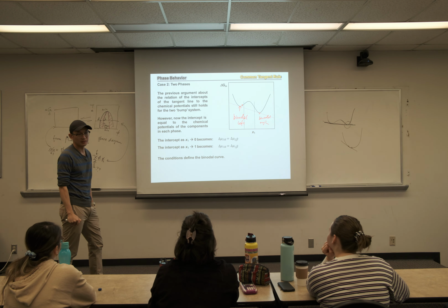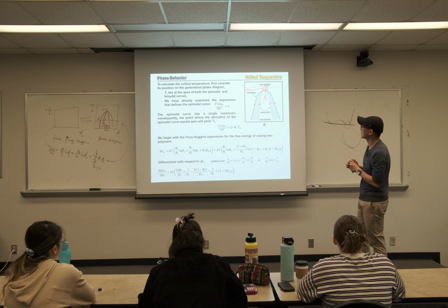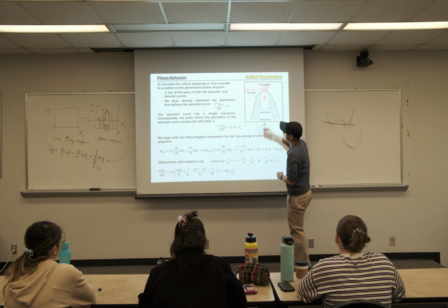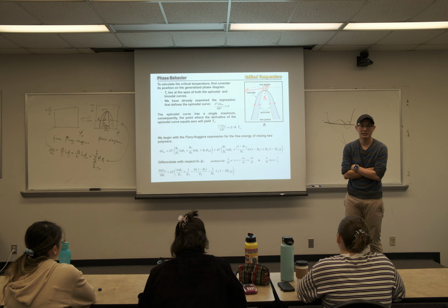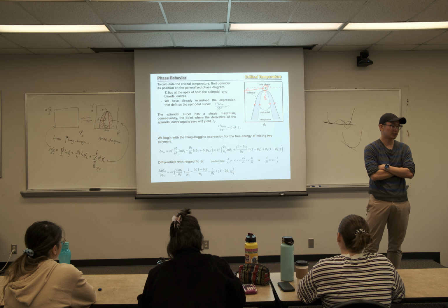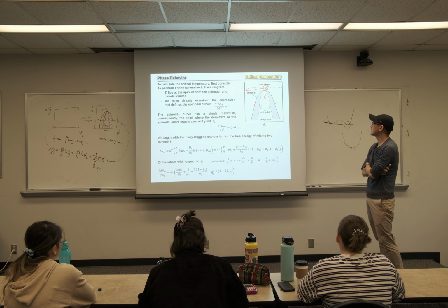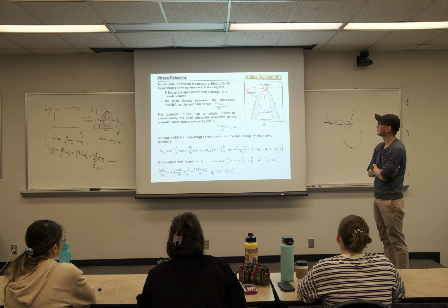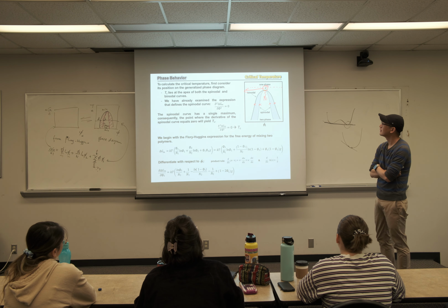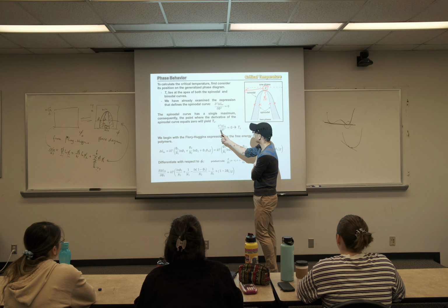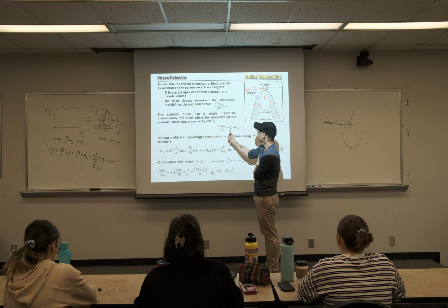And one last thing that we haven't talked about is the critical point, TC. TC is defined at the highest temperature at which you can still maintain phase separation. So it's a coexistence of single phase and two phase. Okay? So TC. And you can get it from the third derivative of G with respect to phi 2 equal to 0.